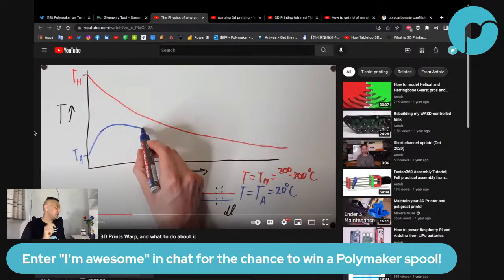Why? Look, I give you an example. I have a hot layer. Okay, let's be here. Exactly here when it started to decrease. I have a hot layer. I put the hot layer on the other layer, and this one starts to cool down. How is that even possible? You put the hot stuff on another stuff, and the other stuff is cooling down. No. As long as they touch, they all go towards the same temperature. If this one is hotter and this one is colder, then when they touch, this one is going to decrease until it reaches this one, and this one is going to increase until it reaches this one. There is no point where somehow this one is going to cool down and this one is still hot. You get what I mean?